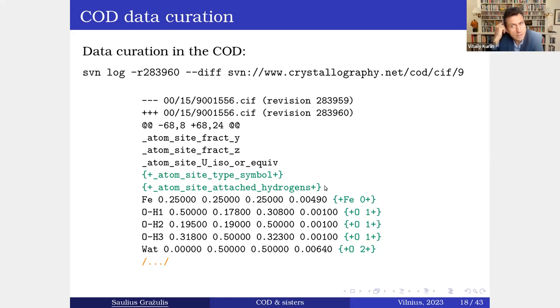And in X-ray data, not necessarily all hydrogen positions are specified. Well, in some cases they are, especially for organics. For some techniques, hydrogens are very well visible. For example, in neutron diffraction, hydrogens are very strong scatterers. Moreover, you have deuterium, where the scattering phase is flipped opposite, so you can distinguish deuterium from hydrogen, but you need a neutron source for that. And it's a much more challenging experiment because the scattering is weaker. So depending on the technique, you might have one piece of information or another in the data record.